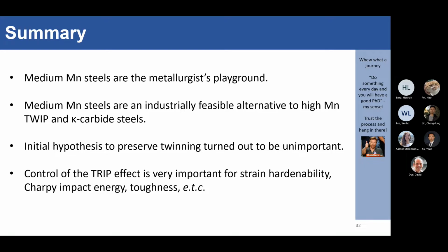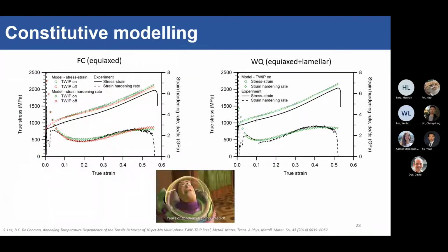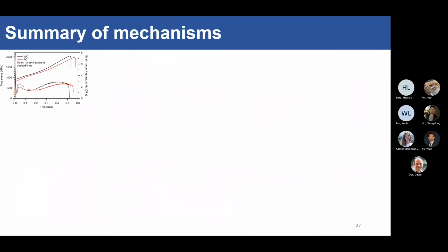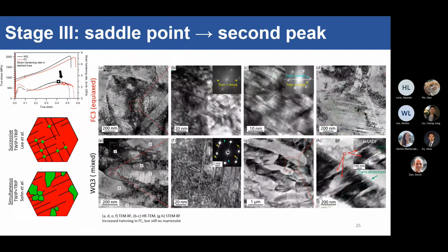So potentially, if you have the double twinning, you will form the epsilon martensite instead of alpha martensite, right? But the double twinning effect, in the medium manganese steels, I see some papers where they argue that the carbon percentage is potentially important for the twinning effect to increase, so that you can have the double twinning of the austenite, so that we can form the martensite in the middle. Yeah, exactly.